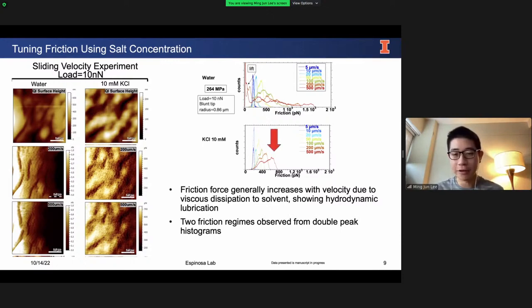And in this arrow here, I'd like to highlight that you can see there are 2 peaks in the histograms, so 2 friction regimes. And I'd like to tie this back to the heterogeneous surface structure I showed you in the initial QI images. I had elevated grains that I believe are the copolymer, and then valleys that I believe are the agarose. So I think that the copolymer is giving me one range of friction values, and then the agarose is giving me a different range of friction values. This could have potential applications in microfluidics, where you might want channels with higher adhesion and higher friction versus lower friction.